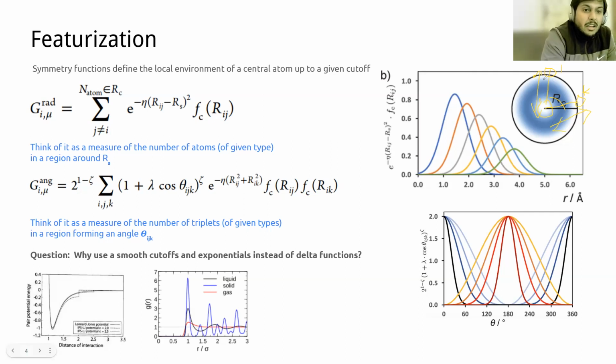So if you have triplets subtending a certain angle, which are really far away, they won't contribute. So somehow this essentially gives you short-ranged three-body correlation functions by construction, so that only the triplets which are close to each other will contribute more. Yeah, is that clear? Yeah, thank you. All right, you're welcome.